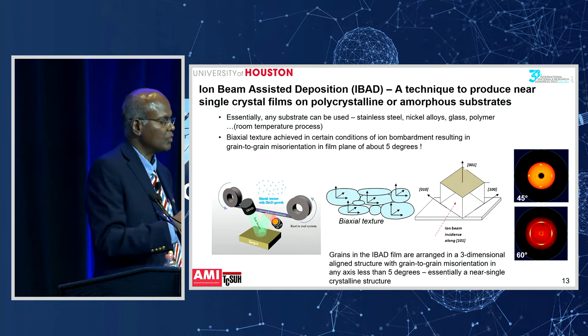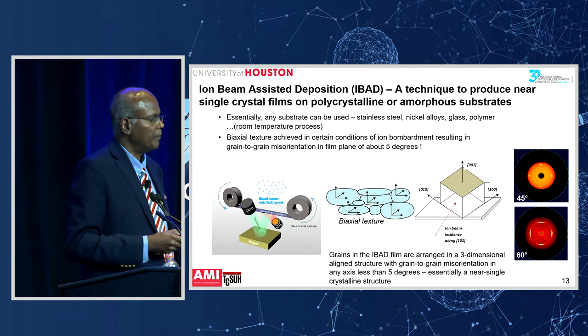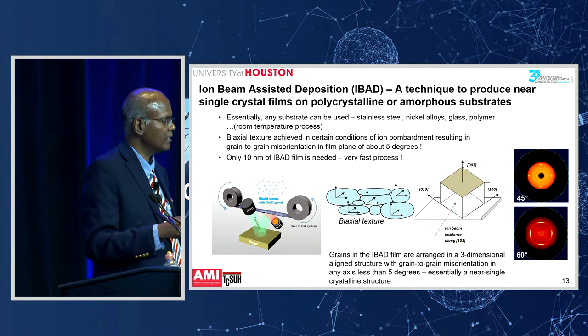If you change the alignment of the ion bombardment to, say, 60 degrees, you can see the texture is not as good. So by this, you can create a nice template where the grains align with respect to each other within 5 degrees. And this is a very fast process because you need only 10 nanometers of this film.